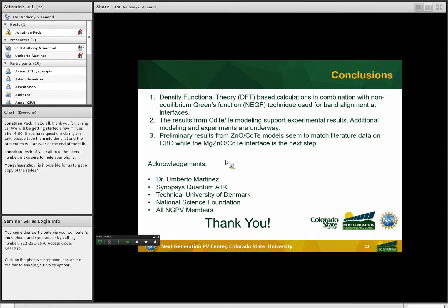In conclusion, density functional theory-based calculations in combination with non-equilibrium Green's function technique have been used for band alignment at the interfaces. The results from the cadmium telluride tellurium model support experimental results. Additional modeling and experiments are underway. Preliminary results from the zinc oxide cadmium telluride models seem to match literature data on conduction offsets, while the magnesium zinc oxide and cadmium telluride interface is the next step.